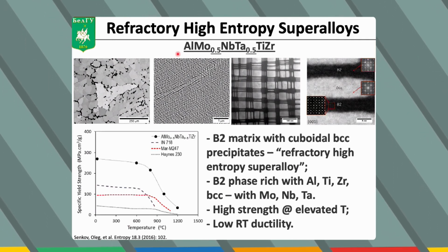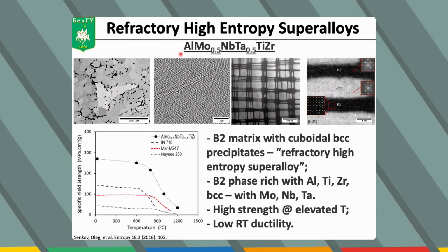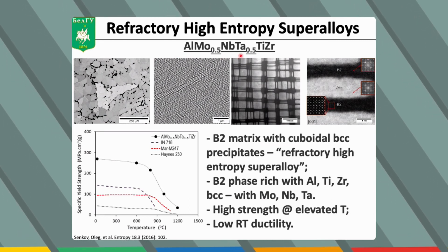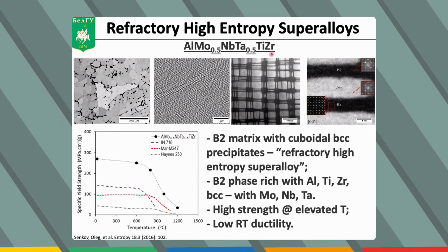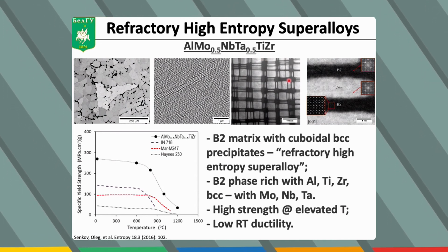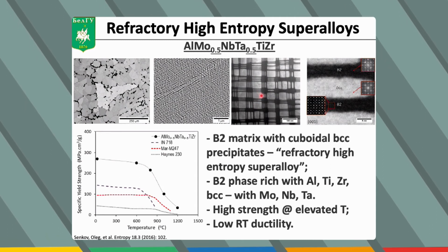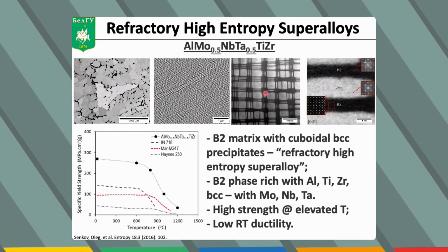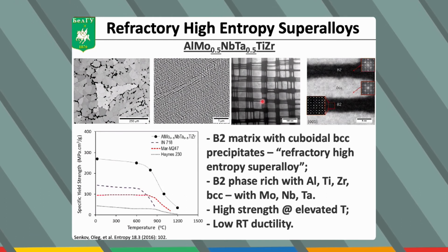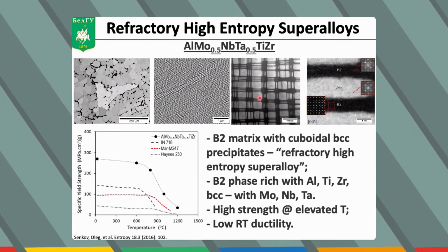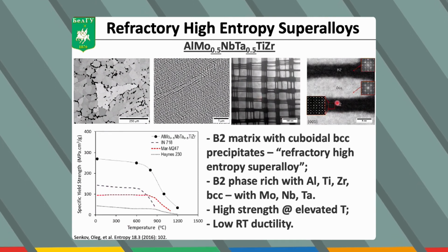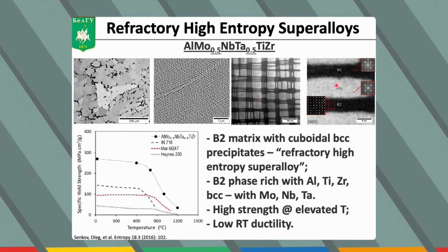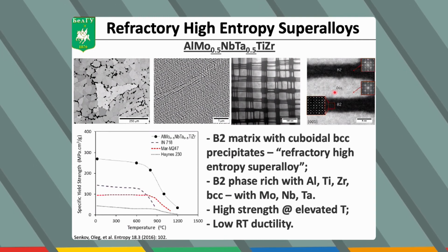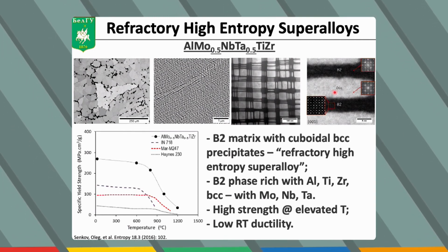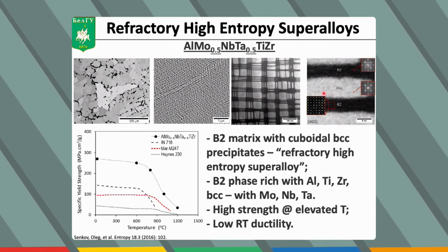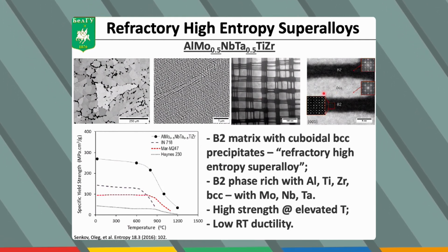And speaking of the potential positive effect of aluminum, I must mention the development of the so-called refractory high entropy superalloys. Here's the example of the alloy composed of aluminum, moly, niobium, tantalum, titanium, and zirconium. You can see at the nanoscale, this alloy has very beautiful microstructure composed of continuous dark matrix and the bright cuboidal or plate-like particles of the second phase. Here, the matrix has the B2 structure and the particles have BCC structure, and this structure is very similar to the conventional nickel-based superalloys. That's why these alloys are called high entropy superalloys.